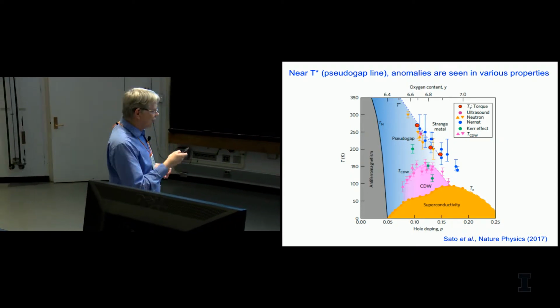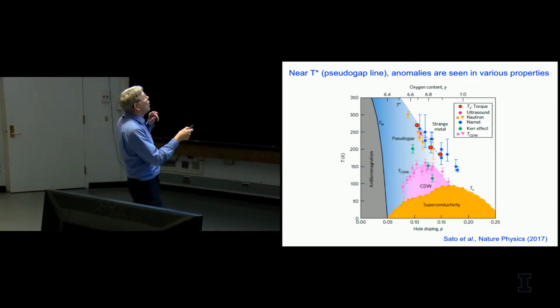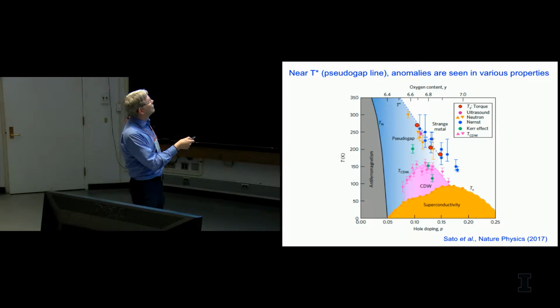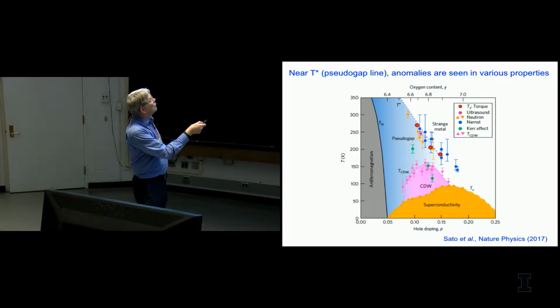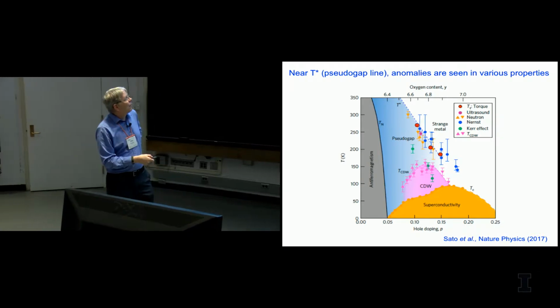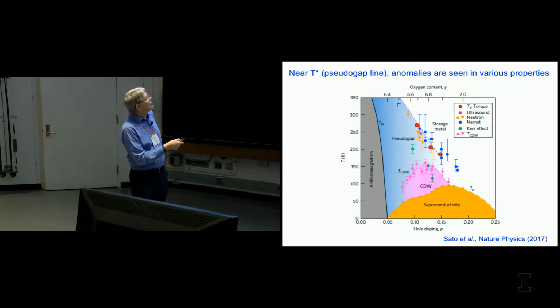Now, perhaps the most studied part of the phase diagram is this so-called pseudogap region. So if you look at temperature versus doping, below some line here, which seems to be more of a crossover line than anything else, you start to see evidence for a large spectral gap opening up in probes like photoemission and optics. And there are various anomalies that occur across these lines or near to these lines that I'll talk about. And over most of the phase diagram, superconductivity emerges from the pseudogap phase. And there's evidence for charge order and other things happening.